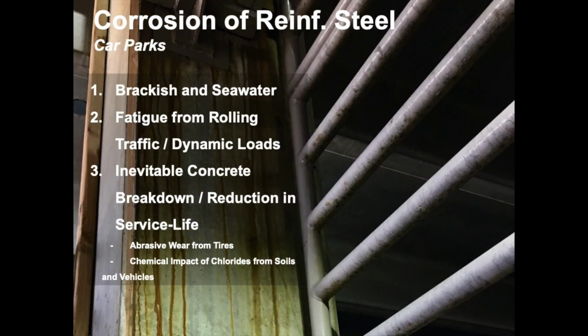Not only do we see this in wharfs and jetties, but we also see this in our car parks, parking garages that might not have that brackish seawater. If they're not located next to the shore, they might just get it from the cars picking it up and bringing it there. But in other areas where you see freezing and thawing, it's more from the de-icing salts and brines. And with the inevitable fatigue and rolling and breakdown, we see the same type of damage, and all this damage goes back to the structural integrity of the concrete.